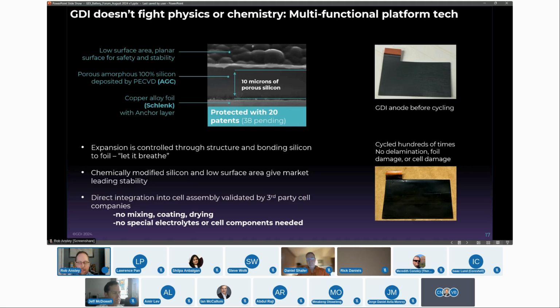Now, let me say very bluntly, if car companies keep pushing for over 500 cycles, you are going to have to use special electrolytes. You are going to have to use pre-lithiation to some degree. That's already been proven by many other companies, such as Amprius, Enovix, et cetera. They all use pre-lithiation. They all use some nice next generation electrolyte additives, and some use a whole brand new electrolyte. And some recent papers have come out saying the future is sulfide solid state, and it's all going to be pure silicon. And Fraunhofer has a great paper about a pure silicon anode against sulfide and how that overcomes a lot of the anode interface issues, because sulfide is not stable with lithium metal.